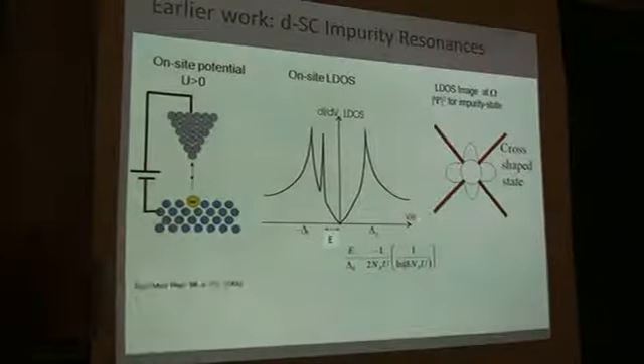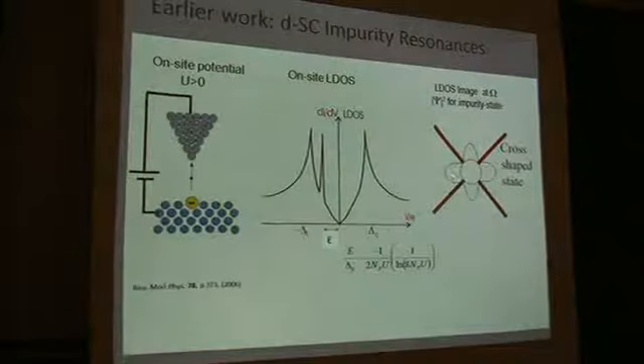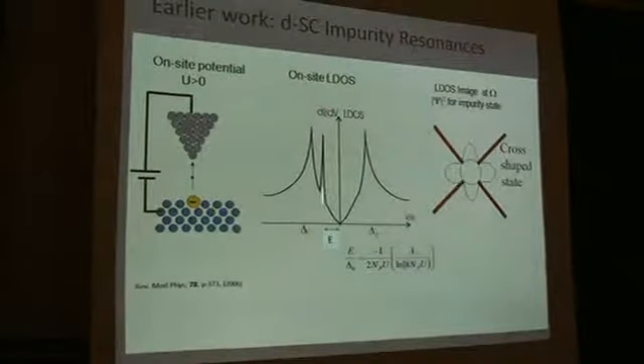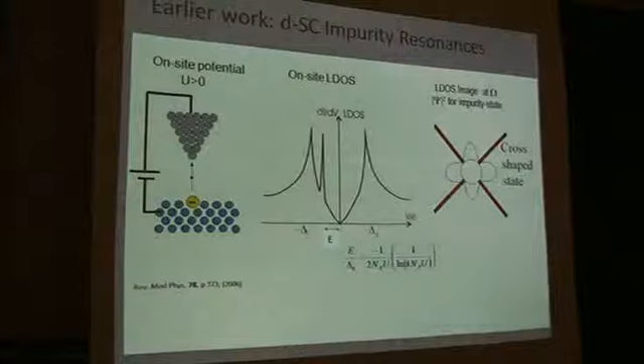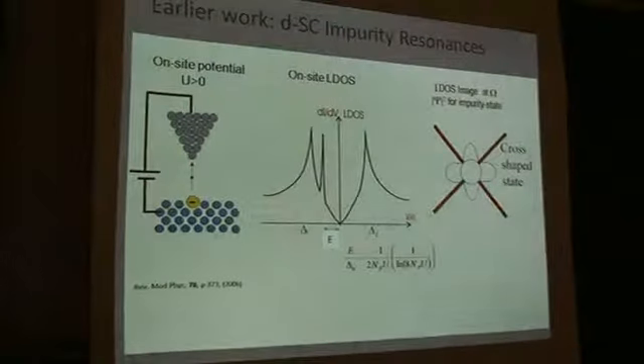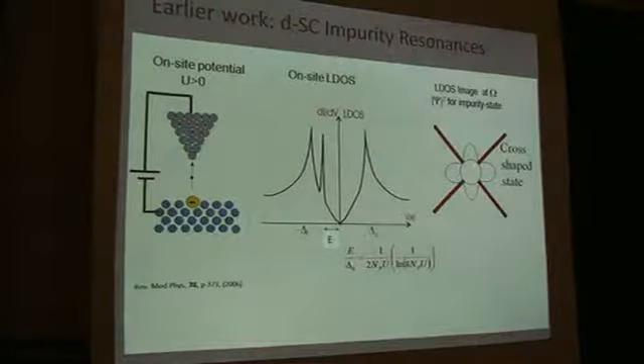Another more exciting proposal at the time was that because I have a gap, and I have an intragap state, like a state inside the potential well, this gap works as a retention wall. It basically confines my state near the impurity, just like I have water in this cup. But if I have four nodes of the gap, the water will leak out. So you can solve the problem of the localized impurity state. You will see that it has four-fold tails, states emanating from the nodal directions. And so the proposal at the time was that by looking at the electronic states near this impurity site, you can infer what the pairing state is, because you can measure the nodes of the gap.